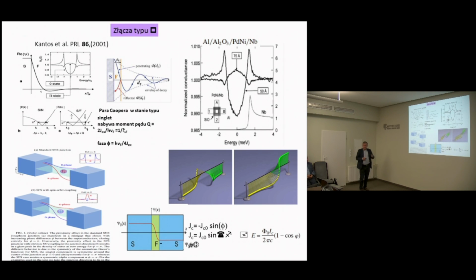I mean, why I'm talking about this, because there are very few ferromagnet superconductor systems. As I mentioned, holmium molybdenum sulfide, erbium rhodium borides, uranium germanium-2, and there are very few. However, due to progress in film deposition, we can make different kinds of structures. And very nice, for example, a very interesting case is the so-called pi junction.